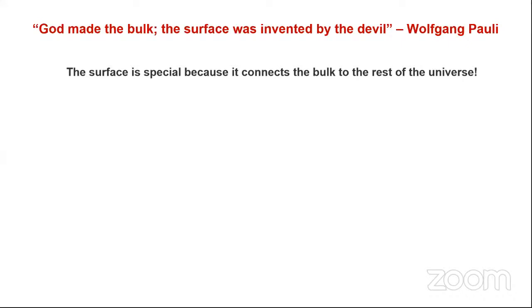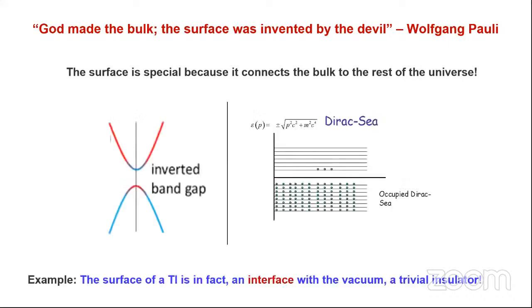Now, I think of the surfaces as the interfaces between a material and the rest of the universe. And that is most beautifully seen in the 3D topological insulators, where the vacuum can be thought of as a trivial insulator. And we have the inverted band gap in the topological insulator. The surface of the topological insulator is actually an interface between the two types of insulators. That's why the interface hosts conducting surface states, the spin-momentum locked surface states. So an interface is always quite interesting.